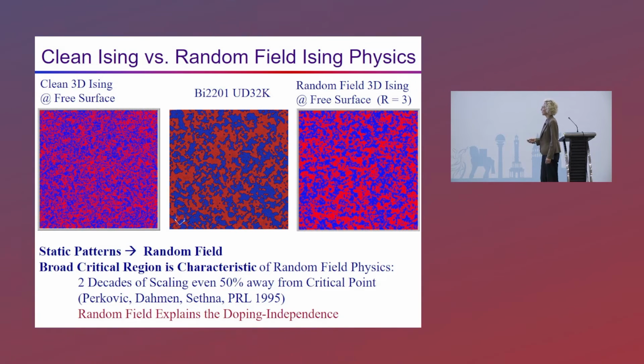Also, the static nature of the patterns is closer to random field physics than to the clean Ising model, which would be expected to have some temperature fluctuations. The static nature here indicates... this is the data in the middle. Sorry, this is BSCCO, the data I showed you before. This is a visualization of textures that would come out of a 3D random field Ising model measured at a free surface. So these are simulations out of my group, or a clean 3D Ising model at a free surface.